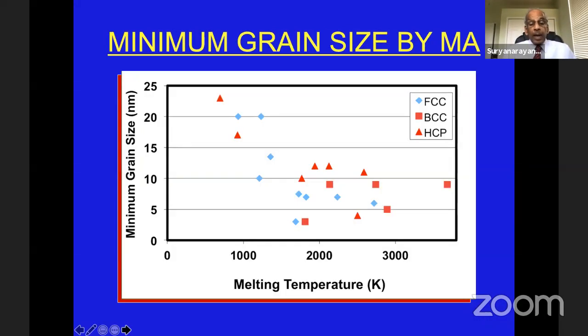And then you can also have nanocrystalline materials produced. Because you're producing a crystalline phase, you can have nanocrystalline materials. Nanocrystalline materials means materials with a grain size of 100 nanometers or less. What you would notice is that by mechanical alloying, it is always possible to produce a crystalline material with a nanometer grain size. So I'm listing here the FCC, BCC, and HCP type of systems. All these values are listed here. You can see the minimum grain size achieved is less than about 25 nanometers. But what I'm showing here is the minimum grain size plotted against the melting temperature of the element.